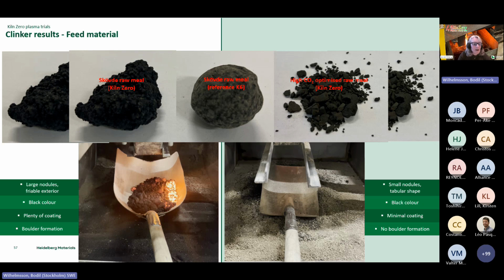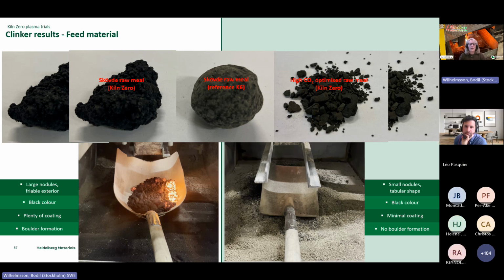We got very nice large nodules, black color, and plenty of coating and some boulder formation. So that was kind of sticky or problematic. But then we could optimize the raw meal, still based on the Skövde raw meal, and then we also optimized it for a CO2 atmosphere, and got much nicer nodules, black color, minimal coating, and no boulder formation.